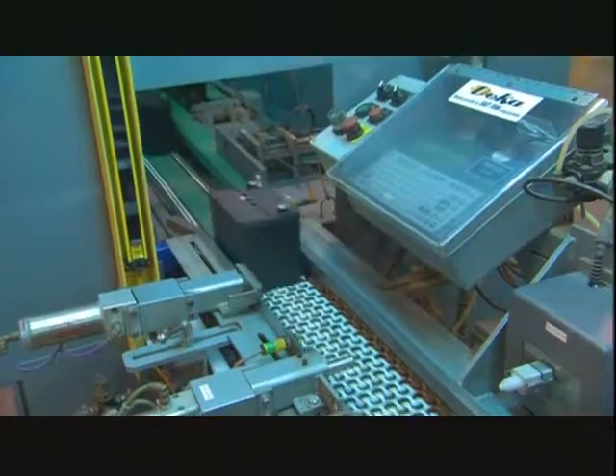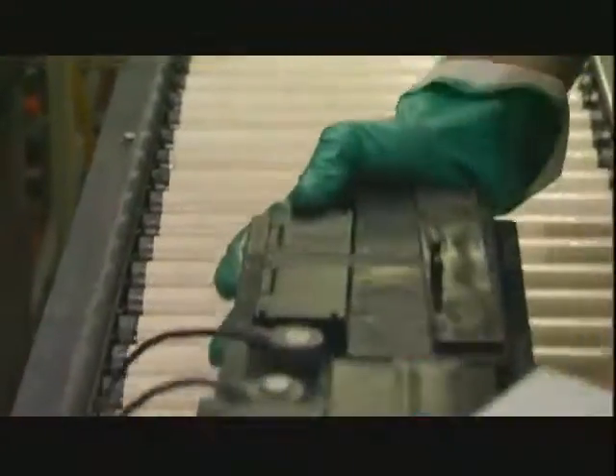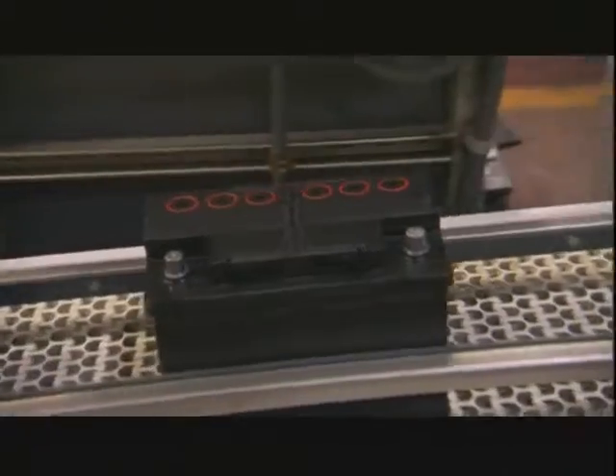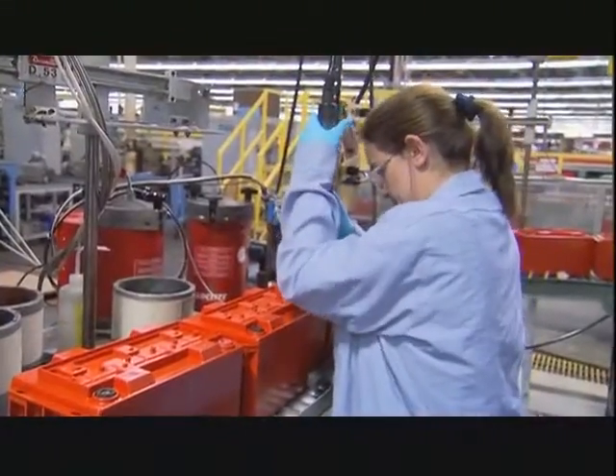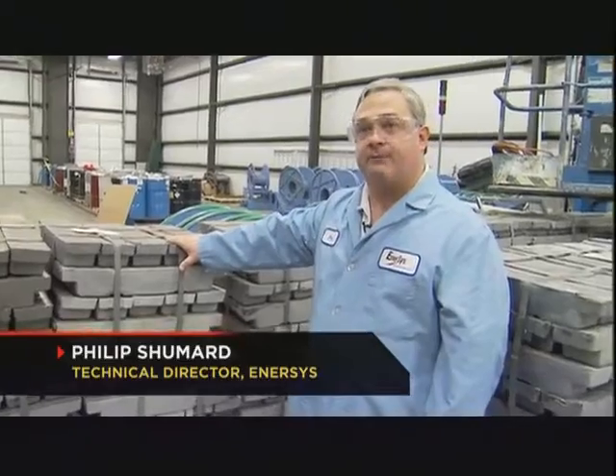To reduce manufacture costs, most car battery makers use recycled lead and lead alloys that contain hardeners like calcium for grids. These substances contain impurities that make the lead corrode faster in its harsh acid environment, which eventually causes the battery to fail. Enersys Energy Products in Warrensburg, Missouri makes a longer-lasting, more reliable battery, and the secret ingredient is virtually pure lead. This is 99.99% pure lead.